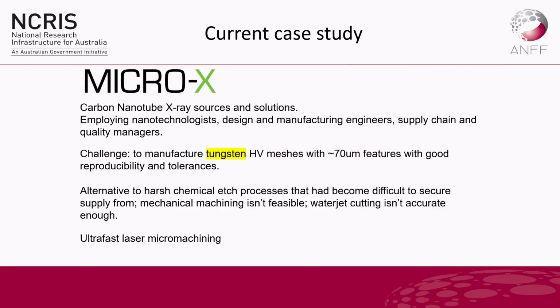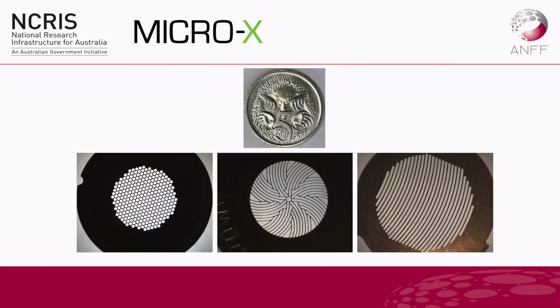It's a very dense material. It's very hard on tooling. And the feature sizes that these guys need are sort of down of the order of a hair diameter. So they want to leave little wires behind which are 60, 70 microns. And that's where the laser machining has really sort of stepped in and made those components possible. So it gives you a little idea of some of the neat designs they've looked at. Okay, these are all machined out in tungsten using the ultra-fast laser process.